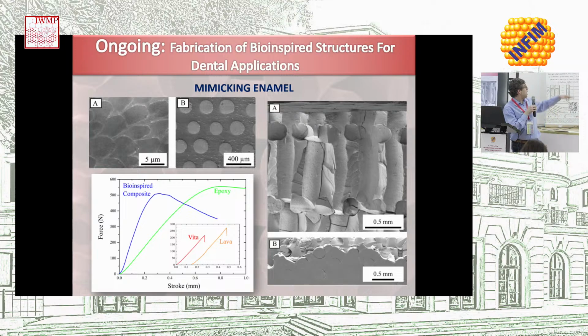And indeed, when you look at biaxial fracture tests done on these structures, these biocomposites exhibit a lot of residual load-bearing capacity after the peak, after fracture. So these materials will exhibit a much better performance than conventional dental materials. Vita and Lava are two conventional dental composites. They are already composites, and they're still brittle because they have a large amount of ceramic, and they show typical brittle behavior. In our case, we don't have this brittle behavior. We have a tough material, even using a relatively unoptimized structure and materials.